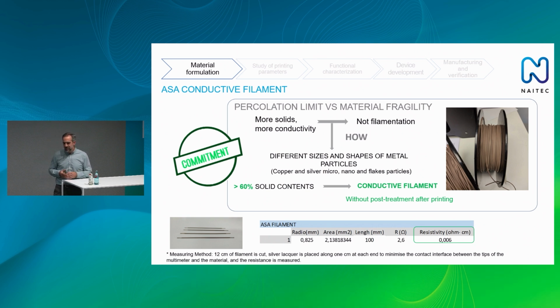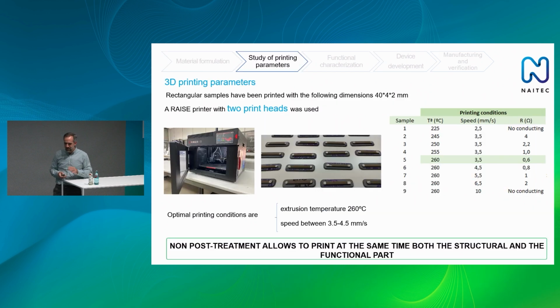The result is a filament that before printing has a resistivity of 6 milliohms centimeter. This measurement is being done with a 12 centimeter fragment of the filament, and we have followed a similar procedure to other filaments already commercial that are in the literature. They characterize the filaments like this, so that we can compare with the filament. And actually, I think our filament is state of the art. I think it may be better.